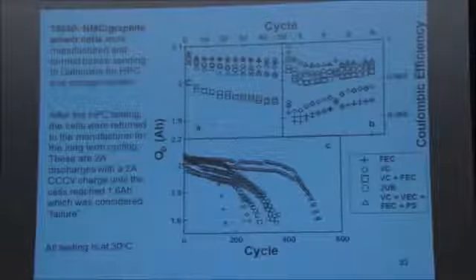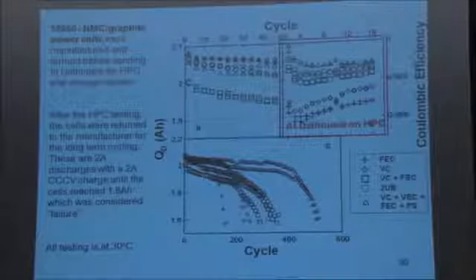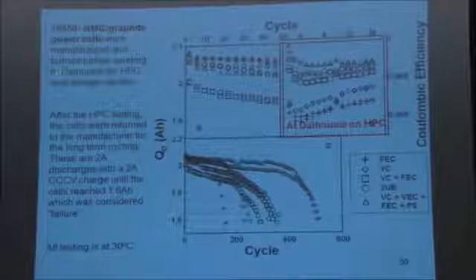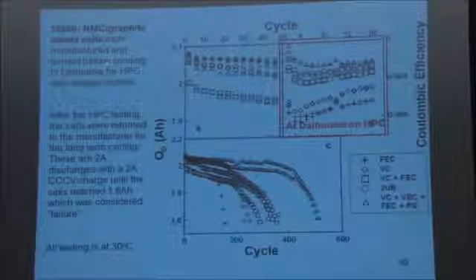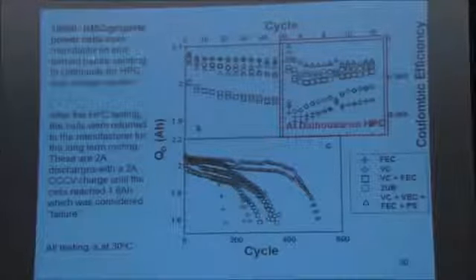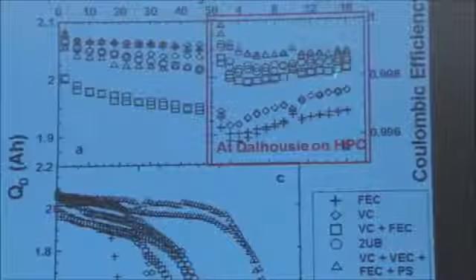Okay, so how did the experiment go with those guys? This is what happened. The cells were manufactured and then they were shipped to us for cycling on our high precision charger, and we also did some storage studies that I won't talk about. So they came to us and we gave them 16 cycles on the high precision station. And here I'm showing you data for 5 different electrolyte additive mixtures. So 4 of them are knowns. This 2UB means 2 unknowns blend B. But you can see the Coulombic efficiencies on this scale vary. So FEC is worse, and then VC plus FEC, and then 2UB, and then these triangles up here.